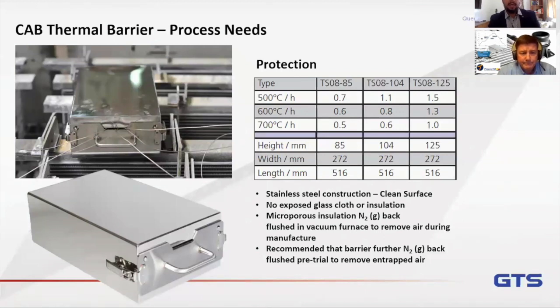By the way, do you recommend to do that also for other types of thermal barriers? Brazing is probably the most classic example where this is beneficial. The obvious downside is you're always fighting in thermal barrier design as to how to reduce the conduction effect. If you put metal around the insulation, you're creating a thermal pathway into the barrier. So we had to be careful how we created that balance between the robust nature of the barrier plus the thermal performance.